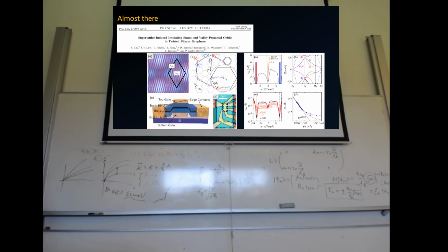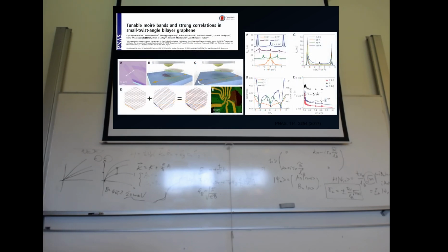What they found is that they tried hard to align, because there were predictions from MacDonald that 1.1 should be the magic angle, where you should see a flat band. They tried hard to align the samples, but they didn't start from a single sheet of a single crystal. They tried to find graphene flakes with straight edges, and when you pick up one flake and then the second one, you add twice the error to twist this angle. So at the end, they saw something very close. They saw some flat band and some interaction-induced insulating band, but there was no famous superconductivity showing up because the angle was not small enough. So later on, there was also some improvement of this system.